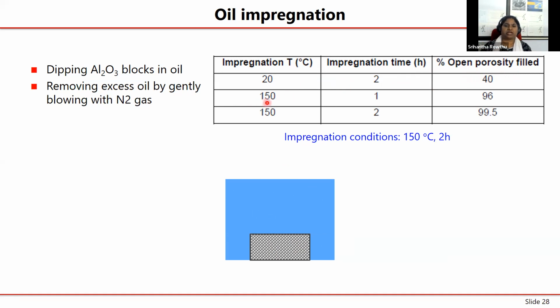Then I said, okay, let me take it to a higher temperature of 150 degrees Celsius. For 1 hour, 96% was filled. If you do it for 2 hours of impregnation, almost 99.5% was filled. Remember that we cannot go much beyond 200 degrees or so, because the oil will start degrading further. So we can say that my optimal impregnation conditions are around 150 degrees Celsius and 2 hours.